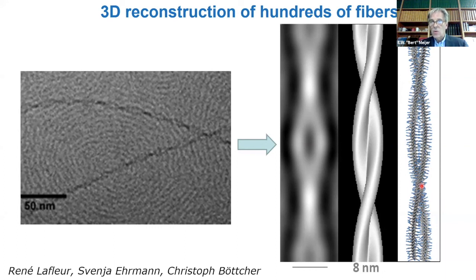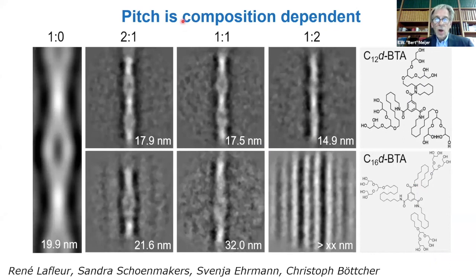And in a way, it even now looks more like a kind of artificial 1D cell membrane. And since it has now that pitch, you can use the pitch by looking at the composition of a copolymer. This is the molecule I just showed you, just a simple thing. It has a pitch length of 19.9, the helix. And then if we mix them with this molecule here on the top, or with this one at the bottom, you will look at what you get out of the cryo-TEM, and you can follow, if you go from here to here, that the pitch lengths become shorter. In the other case, the pitch length becomes longer, even if this one gives you two without actually any pitch. We can't find a pitch.